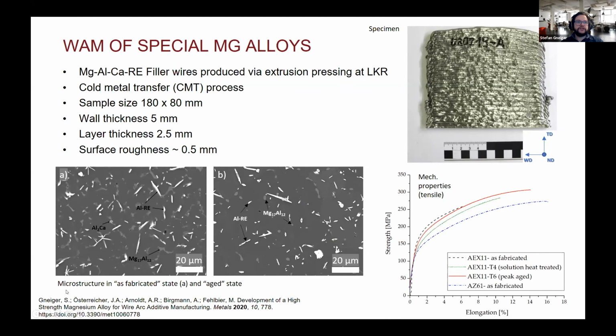And here you can see the microstructure in the as-fabricated state on the left-hand side and in the aged state. This was used to show the potential of heat treatments for additive manufactured parts, and also to evaluate the appearance of porosity, something like this. Here you have these tensile test curves compared to the AZ61 we have seen before. For example, this red line is this in-house produced wire in the T6, so peak aged state. We are almost at 300 megapascals ultimate tensile strength. So with this project, it could be shown that the wire manufacturing route is successful and that the resulting properties can be increased when using special alloys.